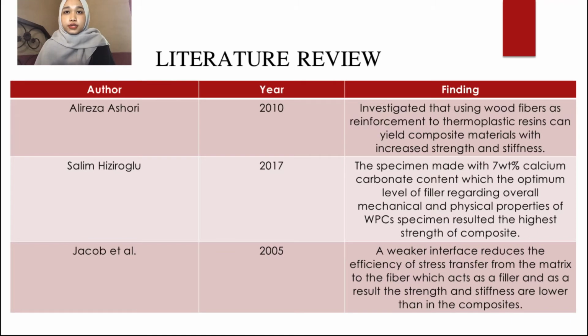Stiffness is lower than in the composite. Ali Riza Ashori investigated that using wood fiber as reinforcement to thermoplastic resins can yield composite material with increased strength and stiffness. According to the researchers, polypropylene granule and rubber wood fiber granule were extruded into rubber wood flour plastic composite granule, and then the compression molding machine was used to make a specimen.